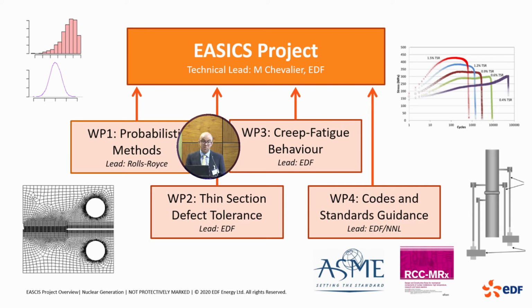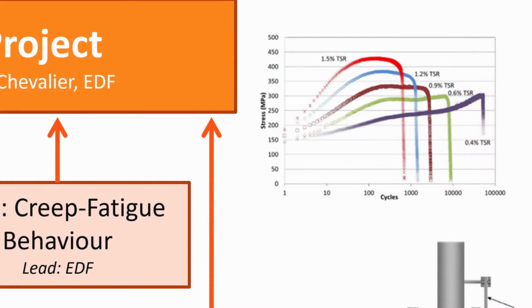We've developed the R5 procedure over 30 years to help improve the methods in this area because it's crucial for operating our current plants. However, one of the things we've discovered recently, in the picture in the top right-hand corner, is that all the codes and standards currently are based on stabilized properties. So that's kind of what the long-term state of the material is, how much it hardens up or softens. And what we can see in the top right-hand corner is it actually takes a long time. That's a cyclic test. So number of cycles along the bottom and basically the strength of the material on the top. It does get harder, but actually for a lot of the life, if you don't have a lot of cycles, it can be quite soft, which means we're massively overestimating the stresses in these components, and we think there's a large margin that we can take benefit from if we improve the quality of the models. So that's what we're trying to do in that program.